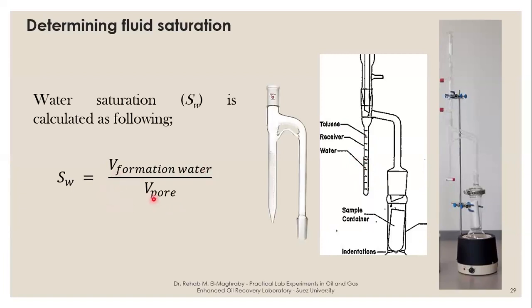divided by the pore volume. Now you can know the water saturation. So what happens is the toluene is heated. As the toluene goes to the top, it will dissolve the oil and heat up the water. All of them will be evaporated to the top and then condensed here, and we collect the toluene and the water in this graduated cylinder, so we can know the amount, the volume of water.